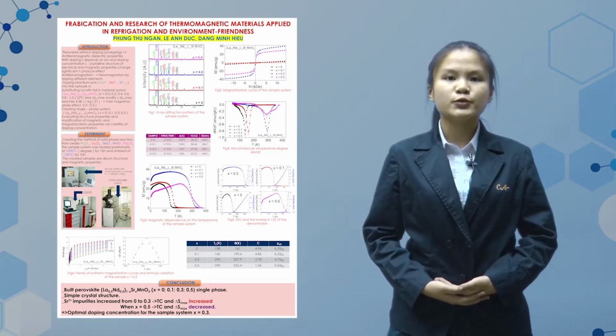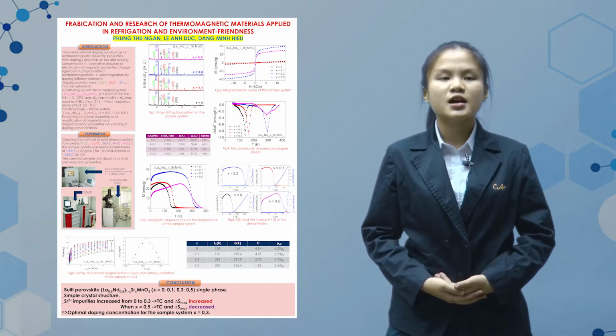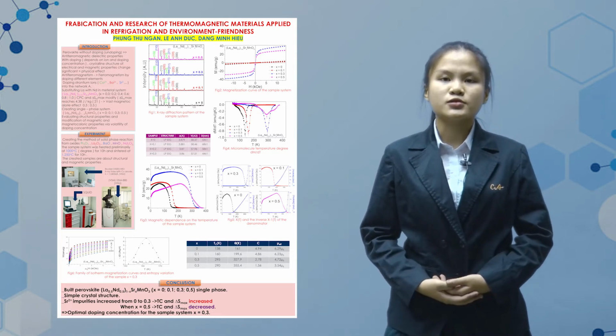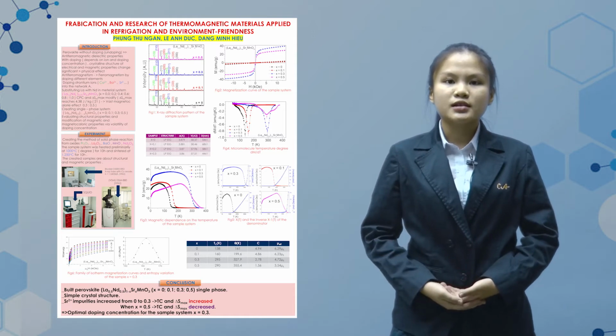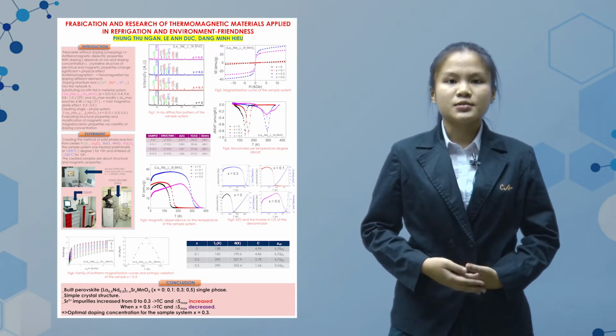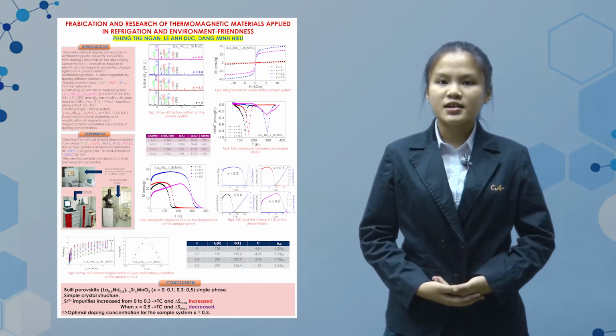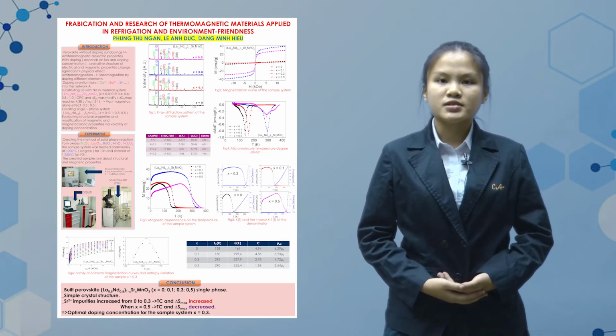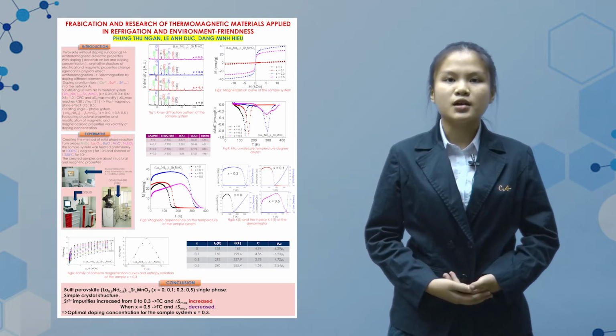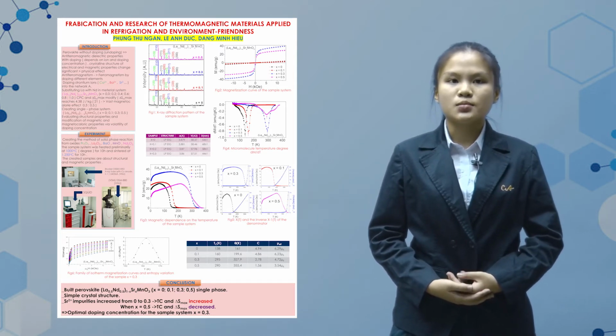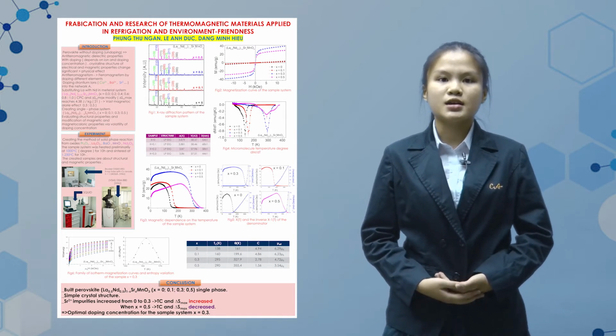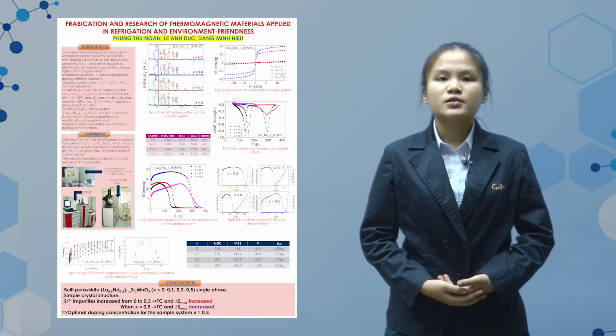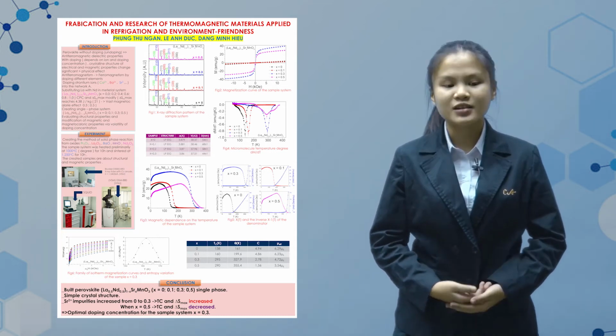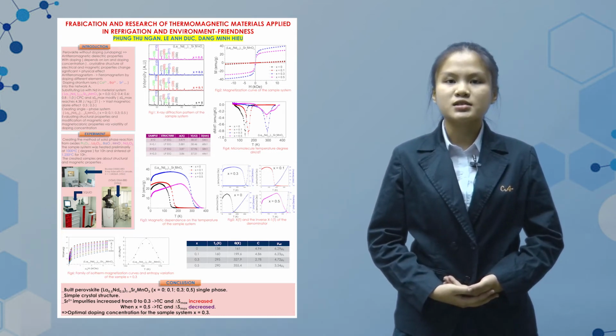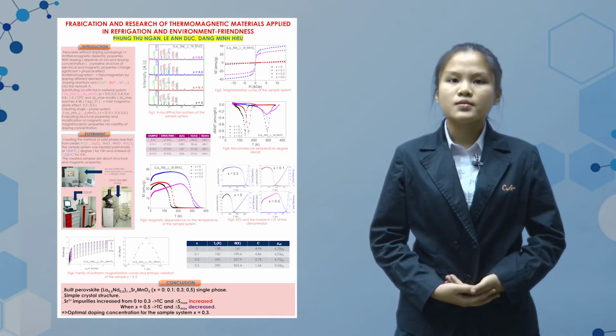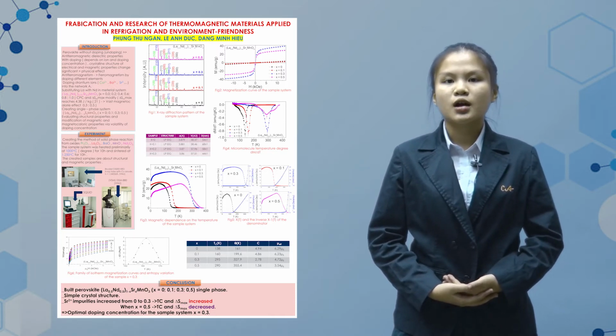Many research groups have doped divalent ions Ca2+, Ba2+, Sr2+ into La. Subsequently, substituting La with Nd in the material system La1-xNdx0.7Sr0.3MnO3, x equals 0, 0.2, 0.4, 0.6, 0.8, and 1.0. So Tc and delta Sm are modified, with delta Sm being 4.38 Joule per kilogram Kelvin. All of them show a vast magnetocaloric effect.